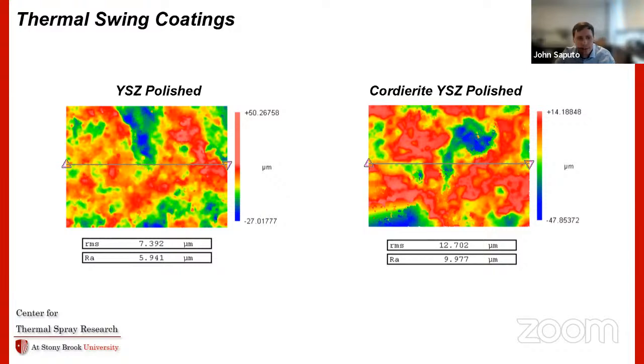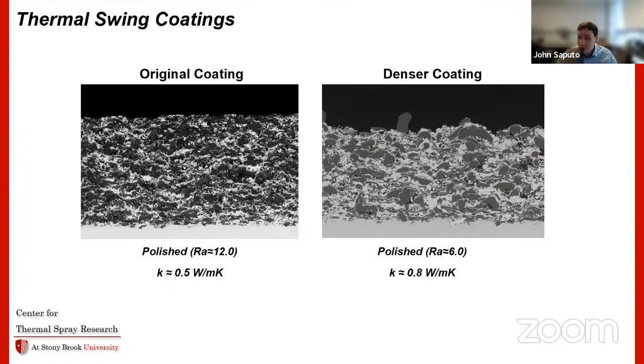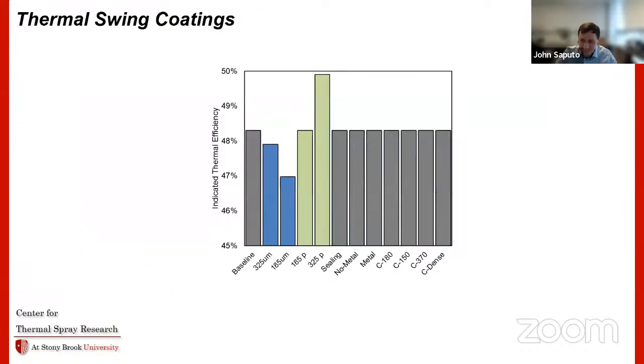It's 9 to 10 microns. So it is a bit higher, and maybe that's the reason. So we got new powders and developed a new spray process. Using a slightly denser coating, you can get lower surface roughness. So I'm showing we were able to knock the final Ra values down to about 6 microns and put this in an engine again. And again, you see absolutely no difference.